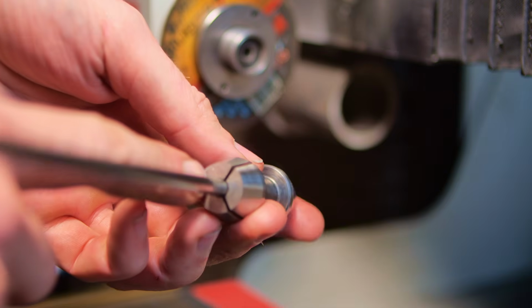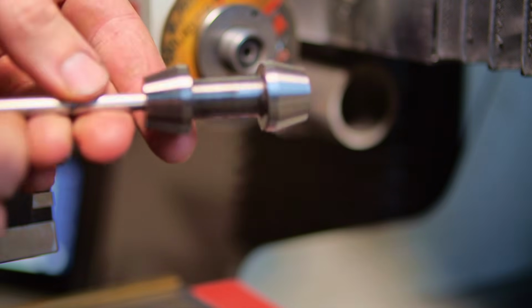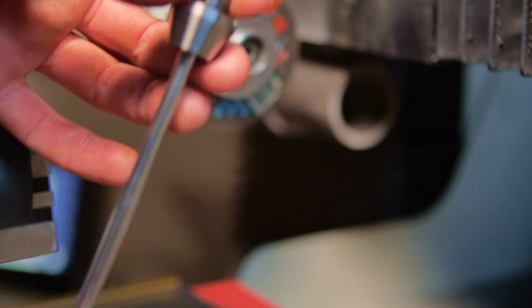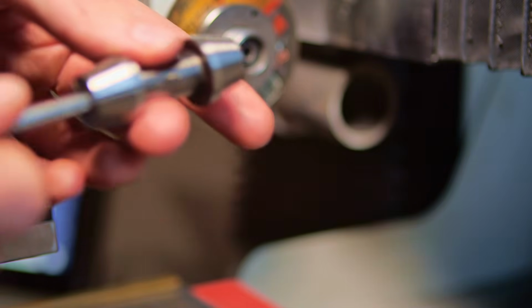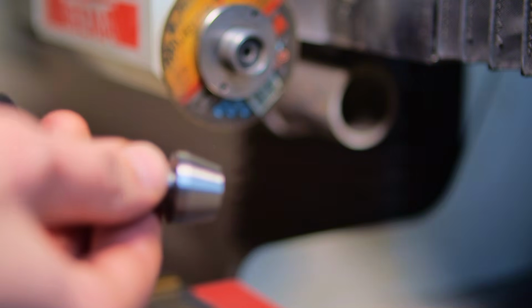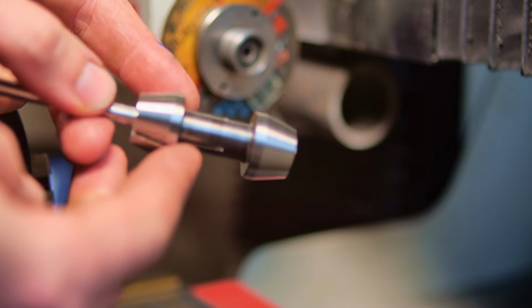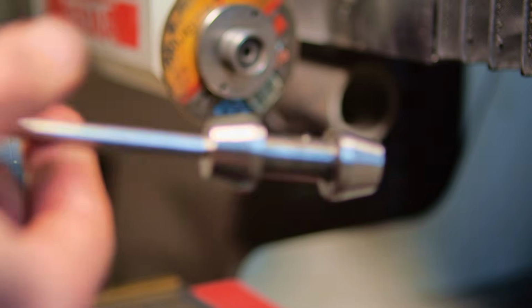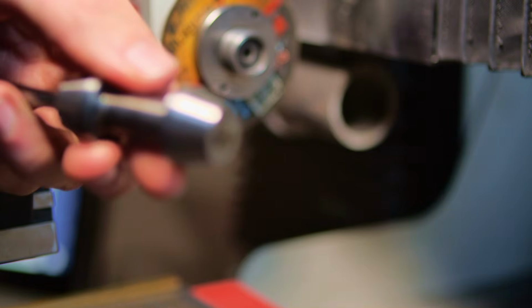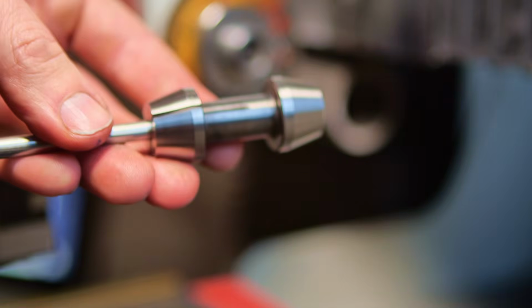So I slit the first side of the collet using an abrasive wheel and a surface grinder, and the part was pushed onto a 6mm ejector pin, and I had some super glue on here, and the end had a toolmaker's clamp, so it can't get yeeted off by the wheel if the super glue fails. That worked okay, but for the second side, I figured I'd take the same ejector pin and I slide the part up all the way to the head of the ejector pin. So it's already captive. Then I take a hose clamp and I clamp the already slit portion of the collet to the ejector pin shaft.